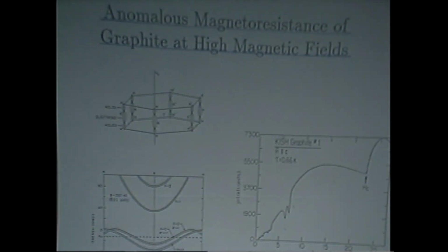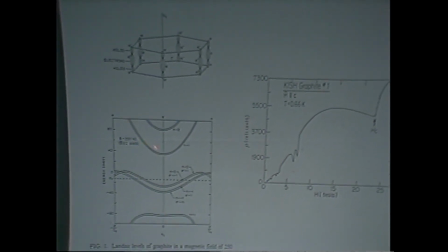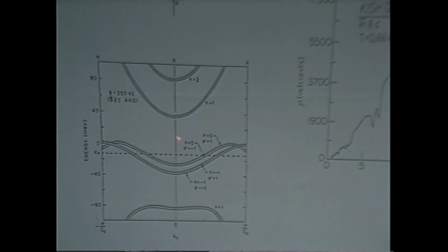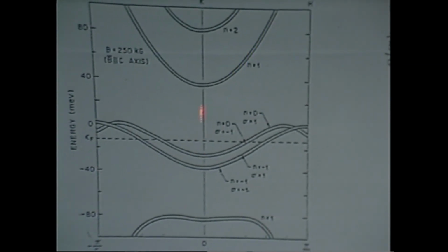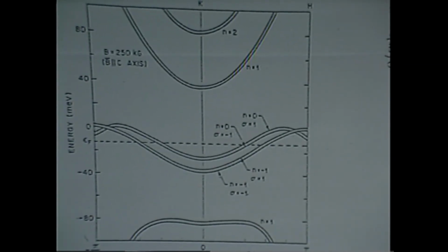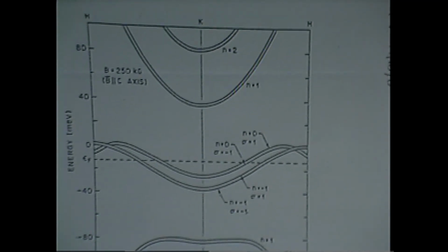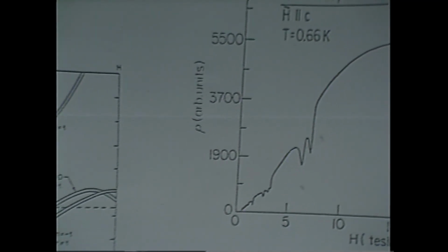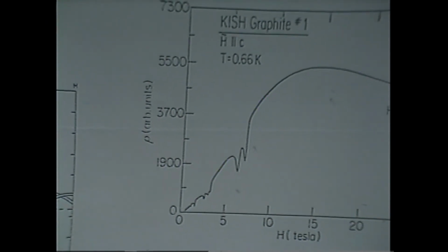And when you think about the problem from a one electron point of view, you have all these Landau levels going through the Fermi level, and the n equals 1 level, that's the standard one. That's supposed to be the last Landau level to go through the Fermi level. That goes through at about 7 Tesla. And spin splitting is a doublet, so you see 2 little pips. And everybody thought that was the end of the story, and nobody really was thinking of looking at anything at a higher field. So the experiments weren't done. And this was like the state of the literature for 15 years.